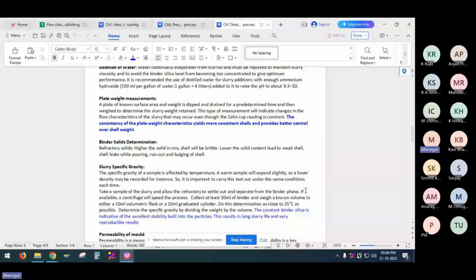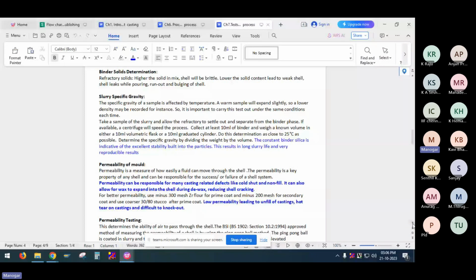Slurry specific gravity. The specific gravity of a sample is affected by temperature. A warm sample will expand slightly, so a lower density may be recorded, for instance. So it is important to carry out the test under the same conditions or a controlled environment.